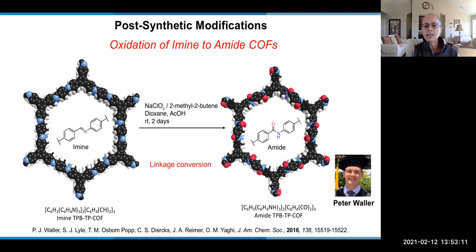But there are some linkages like the amide that don't work de novo. We've tried to make amide COFs and we just could never crystallize them. So one way to do it is to take your imine COFs, which are now very easy to make. I call them the fruit fly of COF chemists. You can make them very easily and oxidize the imine under these conditions to make the amide. Now, the nice thing about this is that you start out with a crystalline material and you don't destroy the crystallinity by converting your linkage under these conditions to the amide. So this is more or less what you would call a crystal to crystal transformation.